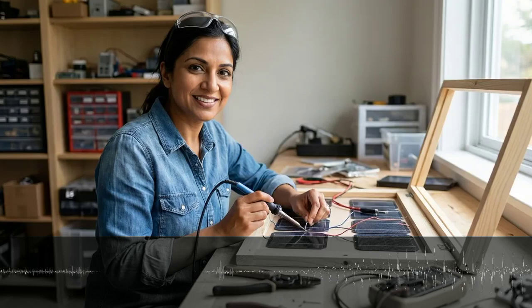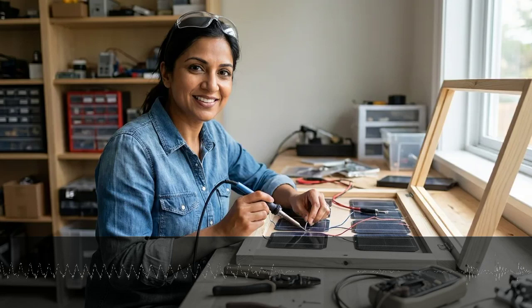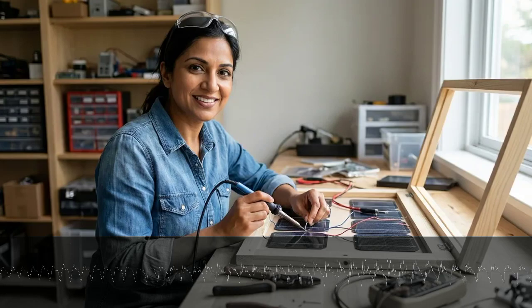Let's talk about some pro tips and common mistakes. Temperature control during oxidation makes or breaks your panel. Too little heat produces incomplete oxidation that won't function as a semiconductor. Too much heat oxidizes so deeply that you get thick, flaky layers with poor adhesion. The sweet spot is full black coloration with oxide layers that naturally curl away during cooling. If your black layer doesn't flake off when cool, you likely didn't heat long enough. The underlying cuprous oxide never properly formed.